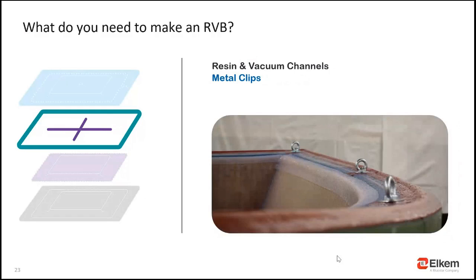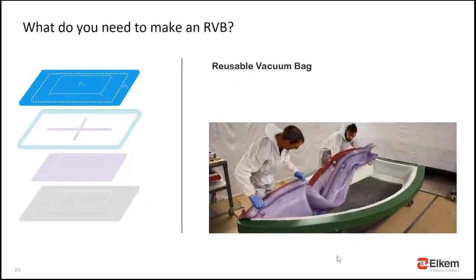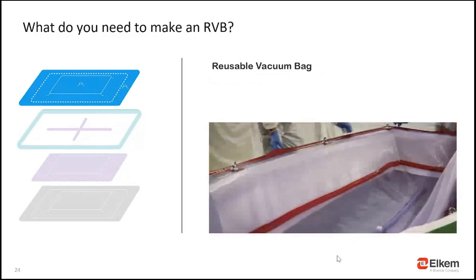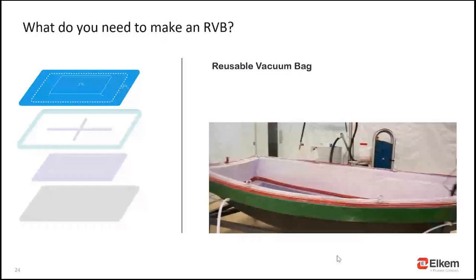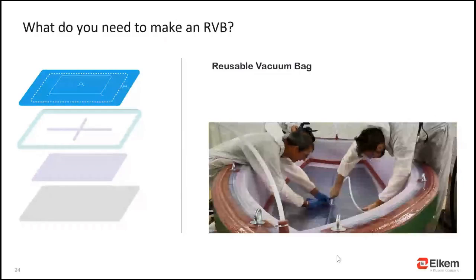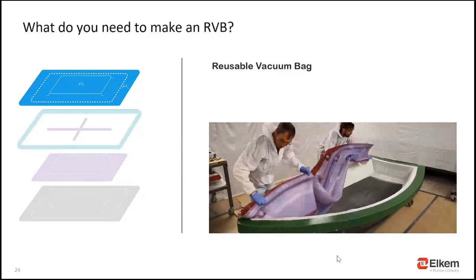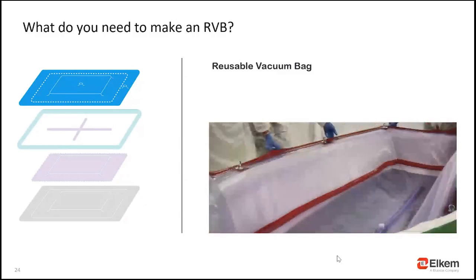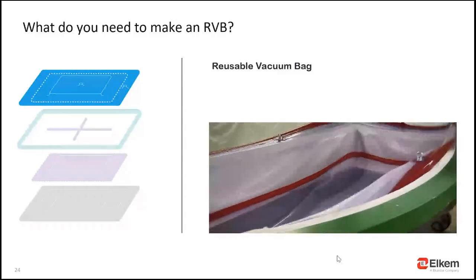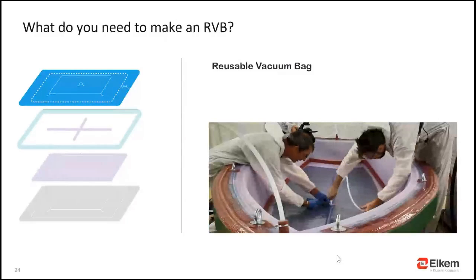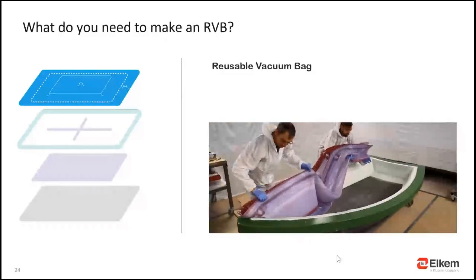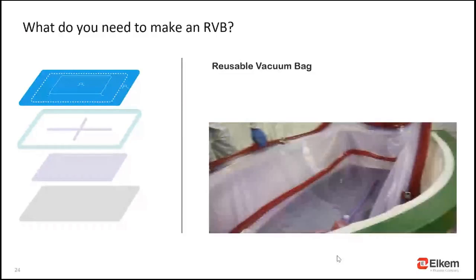For bigger molds and bigger molds only, it's possible, yet optional, to have lifting clips built into the RVB. These metal clips are well known in the industry and help moving the RVB around. The RVB will be made above the inferior rigid mold and a correct composite parting position. This will create the desired space to be filled by the resin during infusion. The final silicone RVB will be a flexible and mechanically resistant mold that's easily moved and positioned. The rubbery aspect of the silicone is ideal to create the vacuum between the RVB and the rigid mold. All this, summed up with fast connection of resin and vacuum, results in one of the fastest mold setups.